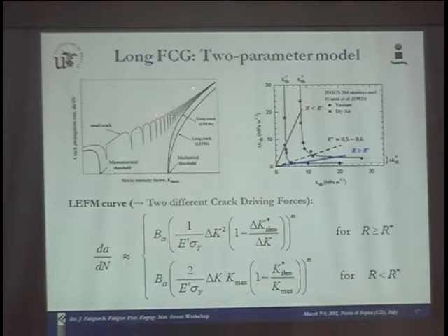To obtain the long crack curve from the small crack curve, the only assumption is to have an infinite number of grains in the plastic zones. Mathematically, that's the assumption. Physically, we don't have infinite, and we need to think of around 100 grains or something like that. But we have not made any other assumption. Just put an infinity in the equation in that case.